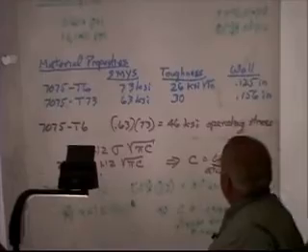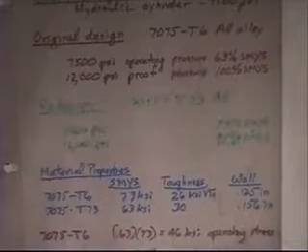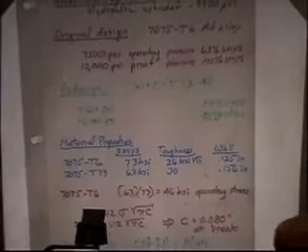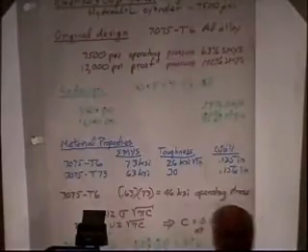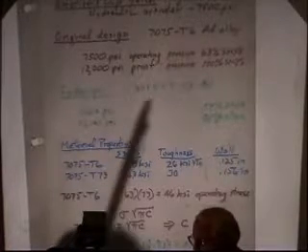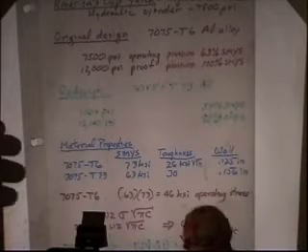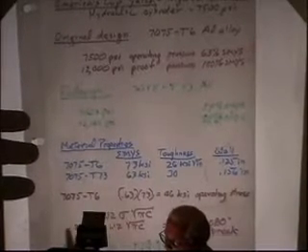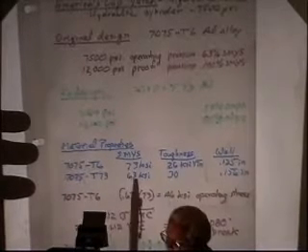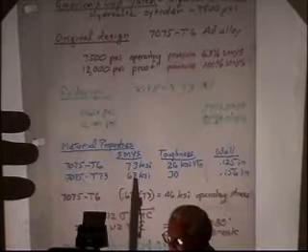In any case, the redesign that I suggested was go to 7075 T73. Now remember that little aluminum washer I said from the helicopter I bought? This was because I had worked on that. And I knew that the 7075 T6 was susceptible to stress corrosion cracking. That looks like a stress corrosion crack to me, but we won't go into that. And so I said, well, go change from the T6 heat treatment to the T73, but the problem is, and you can't read this, the yield strength of the T73 is down from 73 KSI to 63.